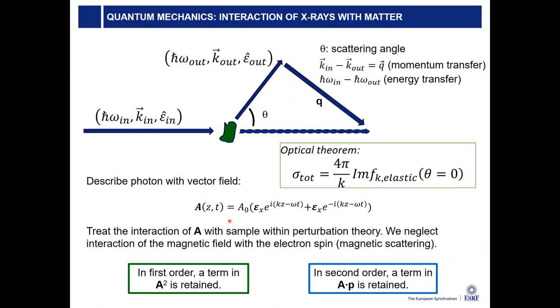This is treated quantum mechanically using perturbation theory, and there are several orders of perturbation theory: the first order and the second order. In the first order, I have an A square term. In the second order, I have an A dot P term. What is important is that A appears differently in the two terms. A little side remark: if you want to relate the cross section I mentioned before for the total absorption, there's a so-called optical theorem that relates the absorption cross-section to the elastic forward scattering in the sample. Forward scattering means theta equals zero.